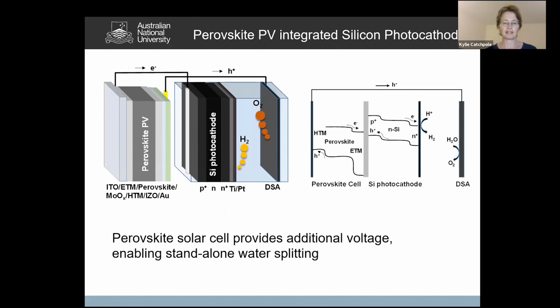So what we've done is we've connected a perovskite solar cell together with a silicon photocathode. Now the perovskite cell is kept separate, and the silicon photocathode is integrated into the electrolyte and then produces hydrogen and oxygen. So in that way you split water. And the important thing is that with this configuration, you can get the voltage that you need, because the minimum theoretical voltage for water splitting is 1.23 volts. So the perovskite and silicon combination is very nice for giving you the voltage that you need.